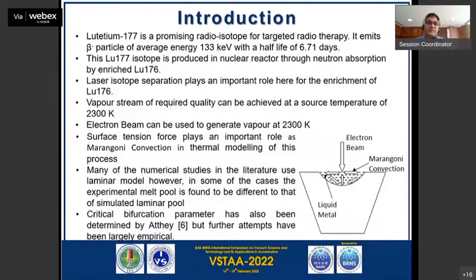In electron beam evaporation, surface tension force plays an important role in the form of Marangoni convection. We can see in the figure that we have a liquid pool with an electron beam striking from the top. At the top surface, due to the temperature difference, the surface tension reduces at the center, due to high temperature, relative to the edge, which is just at the melting point. So the surface tension force causes the liquid to flow from the center outwards, and thus sets up the Marangoni convection.